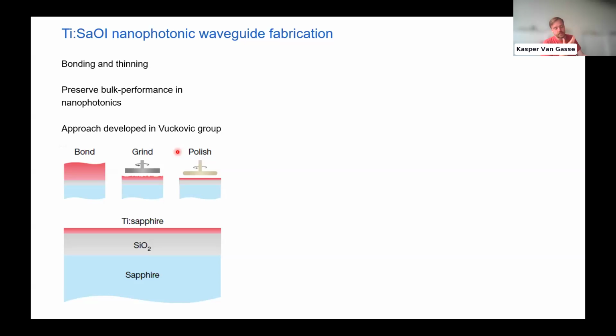But if you want to do color centers in nanophotonics or something similar, the defects you create are too much noise, the quality is not high enough. So an alternative for that is really bonding wafers of material on top of a carrier wafer, and then first mechanically grinding or lapping it and thinning it down, and then finally polishing and/or dry etching to get the nanophotonic thin film that you're looking for.